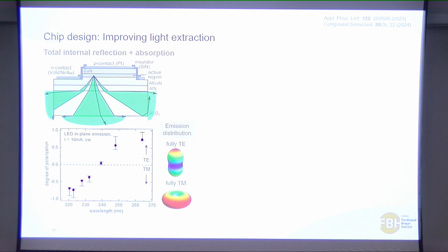And if it was fully TM polarized, then basically the light would be only emitted laterally. And you see that at longer wavelengths, so at around 260 nanometers, most of the light is actually TE polarized. So that's really good when you want to remove light from the LED, because it's anyway being emitted only in the top and bottom direction. The problem is, as you go to the far-UVC region, you're getting more TM polarized light than TE polarized light. That means it's becoming even more difficult to extract light from the LED, because it's basically being emitted laterally.